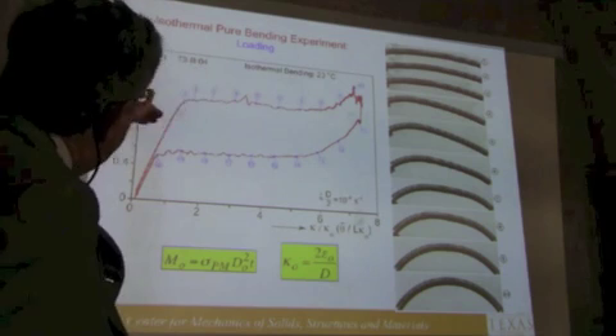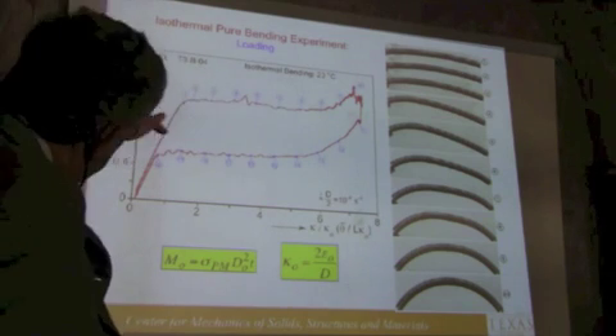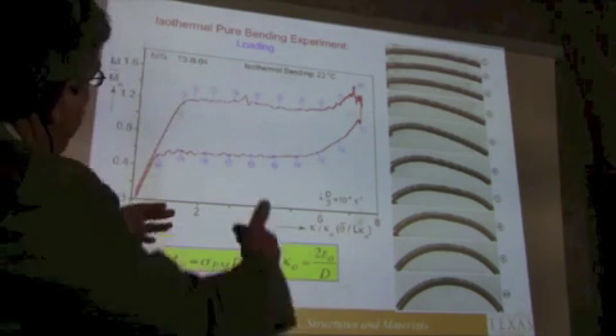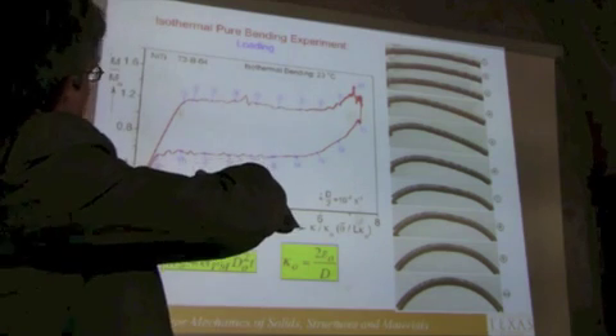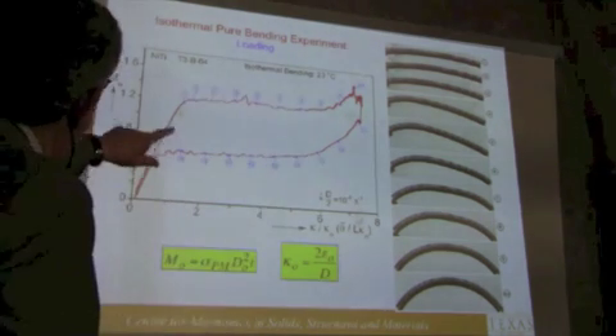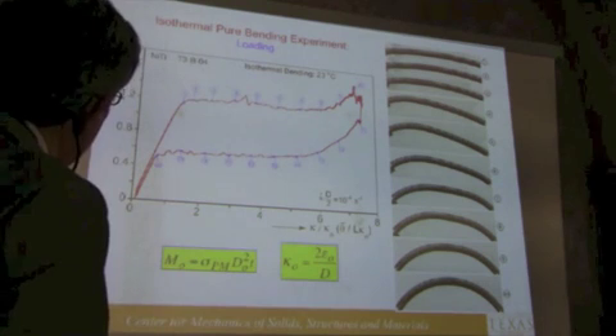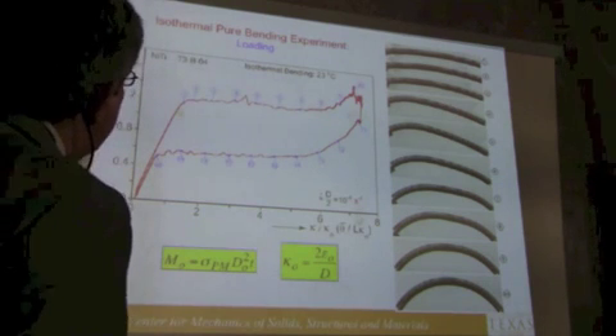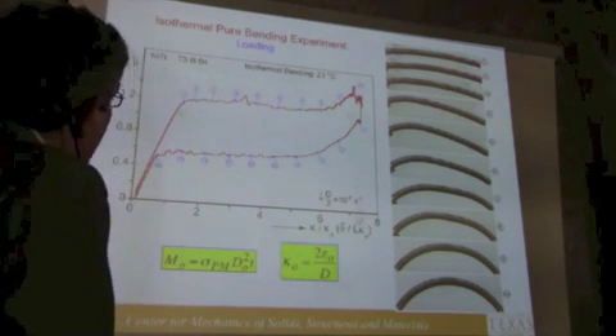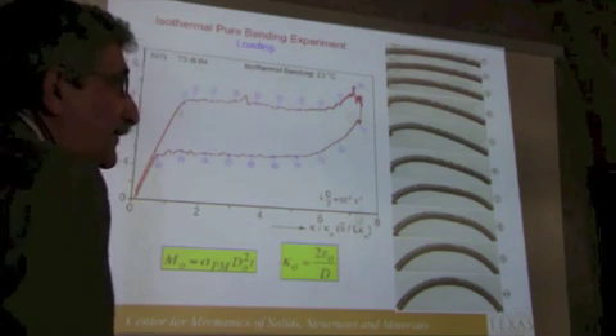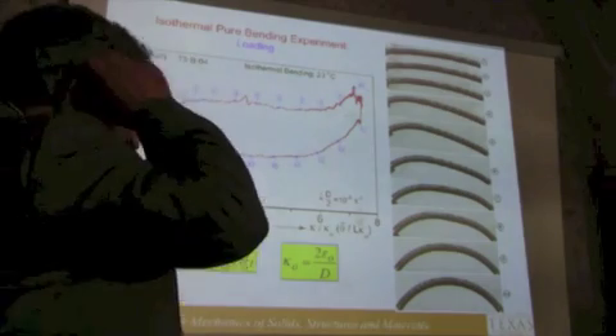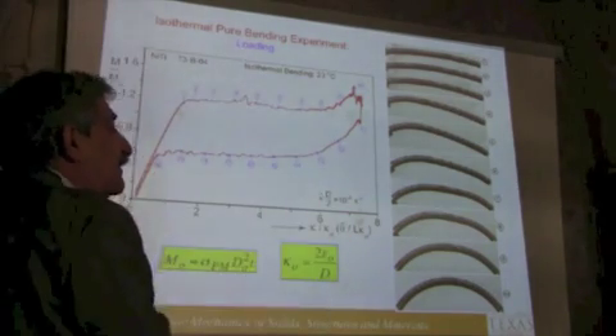I am not showing to you the unloading, but the unloading has another plateau during which the two curvature regimes show up again, and then of course we're able to close the loop because this is a pseudoelastic material. This is a problem that requires solution, and we don't have one. I think I'll stop there and let you go to lunch. Thank you.